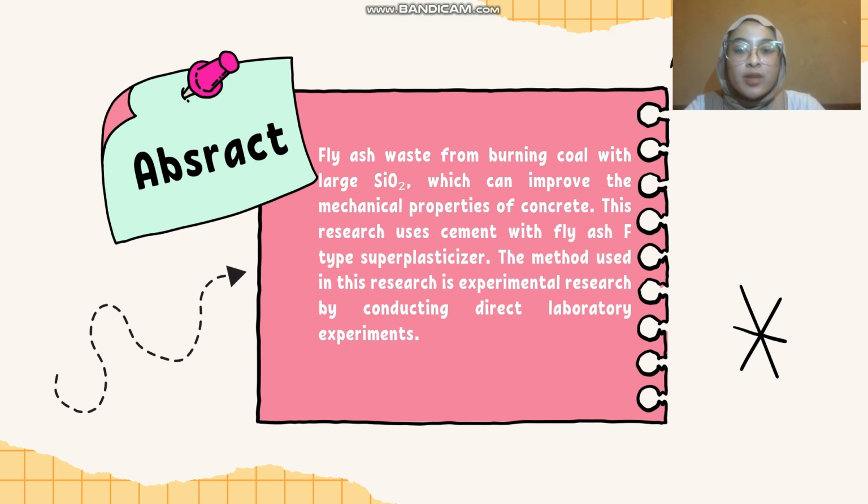superplasticizer. The test objects were burned at a temperature of 300 degrees Celsius for more or less 2 hours at the age of 36 days, after which the compressive strength was tested.